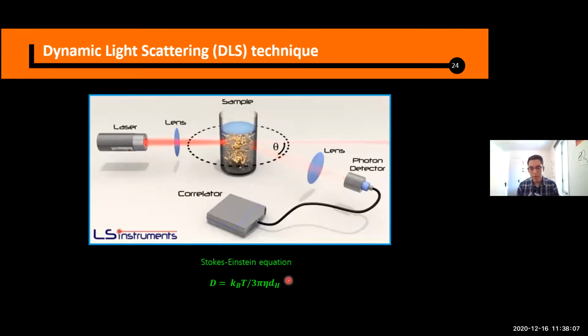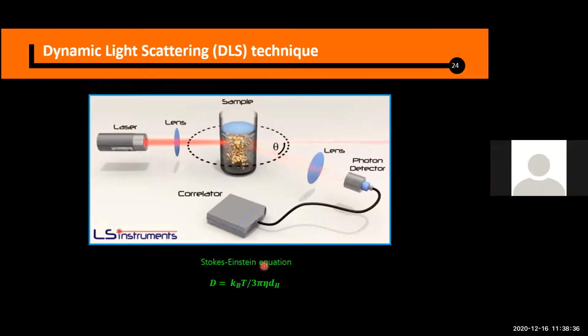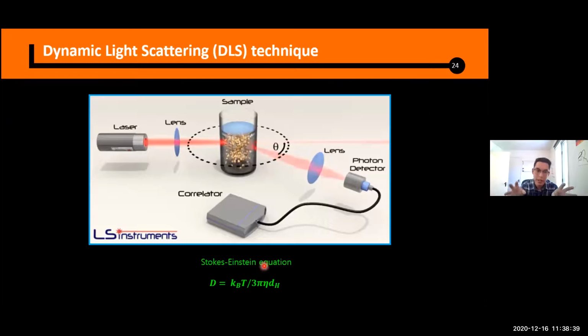In principle, the hydrodynamic diameter is defined as the diameter of a sphere that has a specific translational diffusion coefficient. So with this value, we are measuring the Brownian motion velocity, and with this equation we ask, okay, with this value, what should be the particle size, or the sphere, that has the same translational diffusion coefficient, and then we can make the comparison between the two samples.